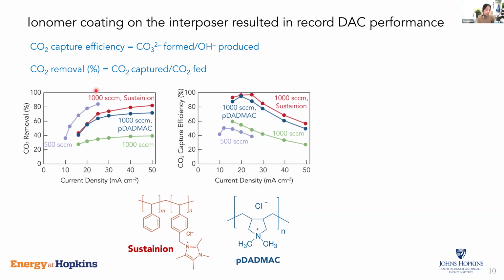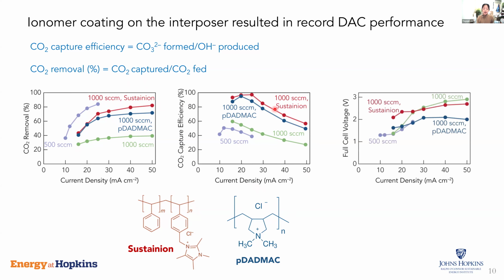As you can see, with the ionomer coating, we further promote the transport of hydroxide and carbonate in our resin wafer, in our interposer layer, and also improve the solubility of CO2 in our interposer layer. So with that, we can further improve the CO2 removal at high current and the CO2 capture efficiency, which is really promising. Another advantage of introducing this additional ionomer coating is that we can reduce the full cell voltage at higher current density, and that translates to lower voltage or lower energy input.